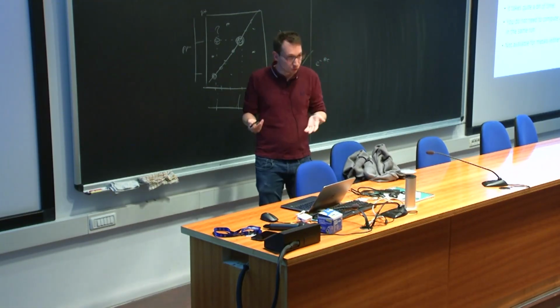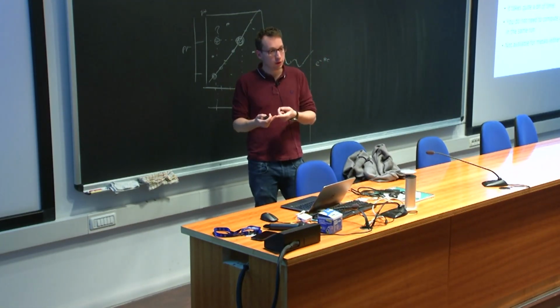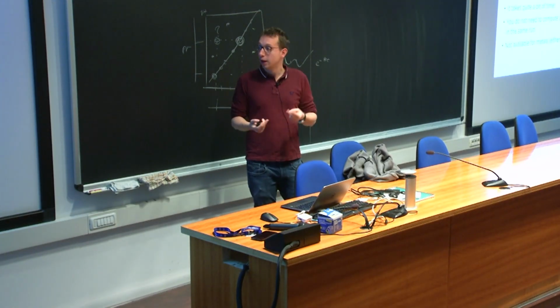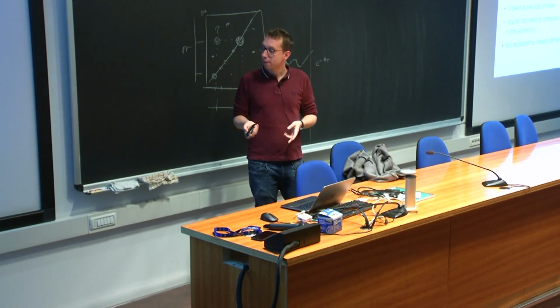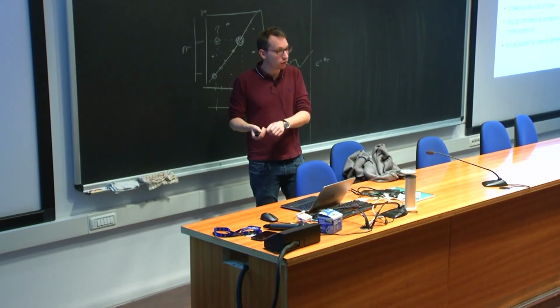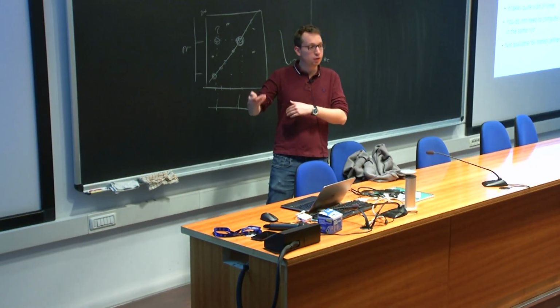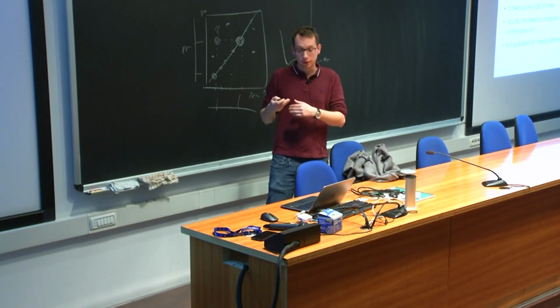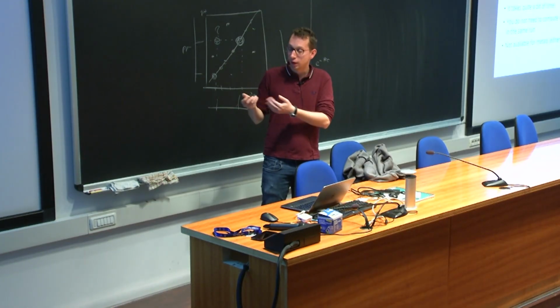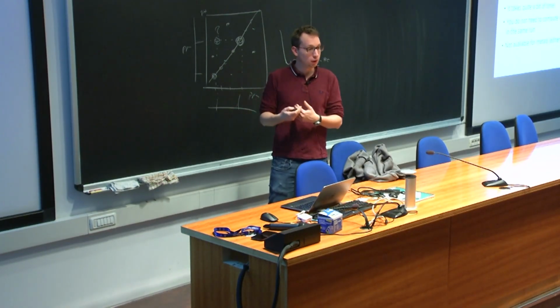But if you know what you're doing, if you're sure that the smearing is not a real smearing, you can just go inside the code, change the check, and let it compute epsilon anyway. And it will, of course, ignore the effect of partially occupied bands. But when you're using a smearing and your system is not really a metal, it should be 0 anyway.